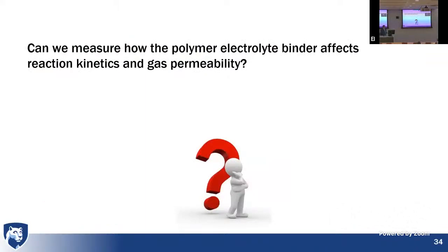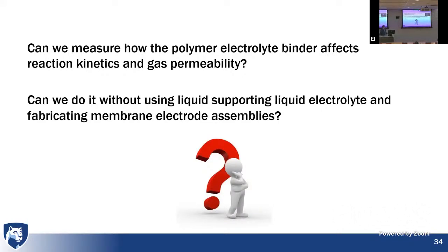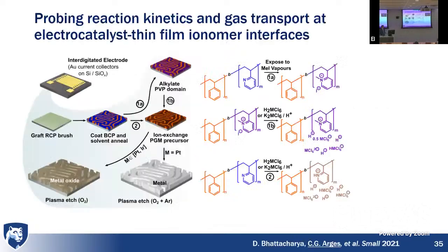So how can we measure these properties for these thin film materials and electrodes? And can we do it without having to make an MEA every time, or going to the rotating disc electrode where there's liquid supporting electrolyte that will obfuscate the parameters that we're really interested in, under the conditions we're interested in, which is with no liquid? So my student Deepa again, he made these interdigitated electrodes using optical lithography. And here we used incipient wetness impregnation to decorate, using the block polymer template, to put this electrocatalyst on the electrode surface. So once we put this block polymer in there, we put these metallochlorates, they exchange into one block.